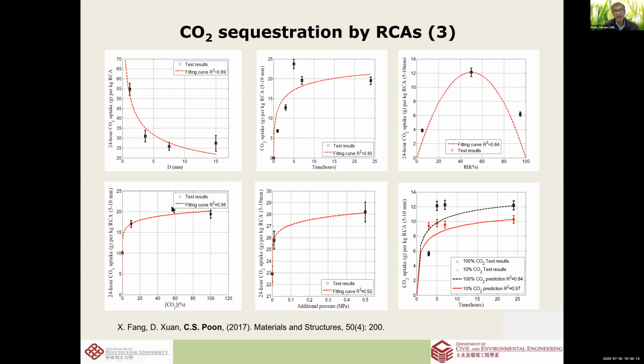And then we found out that a few hours, maybe 1 day is enough, or even less than 1 day, because the carbonation reaction goes through this slowing down process. And also the CO2 concentration, there's 100%, and this is about 10%, and this is 0%. And we say, okay, 10% is good enough already. So in real flue gas, in some off gas from, for example, a power plant, it is about 20% CO2. And pressure-wise, some pressure is good, but without pressure is okay. We think that even under atmospheric pressure is okay.